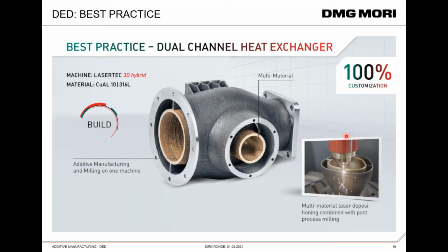You know the powder bed machines, everybody knows it's a single material process. Due to the fact that we blow the material in our machines from the hopper to the melt point, it makes it possible to switch even in one layer or from layer to layer the materials. We have a twin feeder system in our machine, and we are able to mix the materials. And here you can see a stainless steel body, which is a tube-in-tube solution, and we have a bronze for the inside, and we switch the material from the outside to the inside in one step, which is a simple blowing impulse to clean the feeder or the feeding tubes and to load the new material.